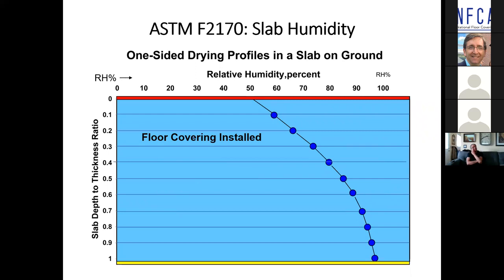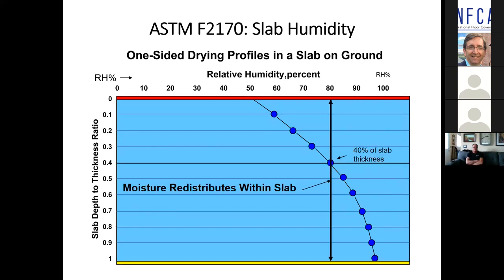Now you come in and you install your floor covering. And as we talked about earlier with the slab curling, that curve, that gradient, will now reestablish itself as a state of equilibrium. But because we've lost a measure of moisture, that state of equilibrium will be at a lower RH level. So in this case, it's 80%.